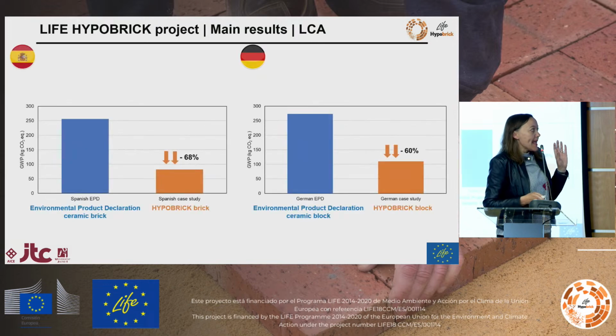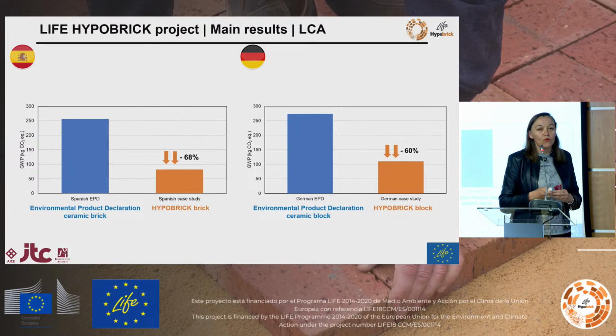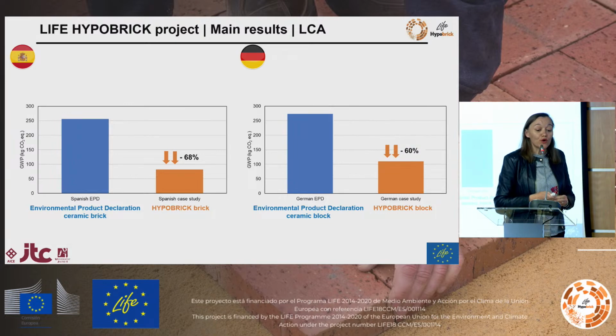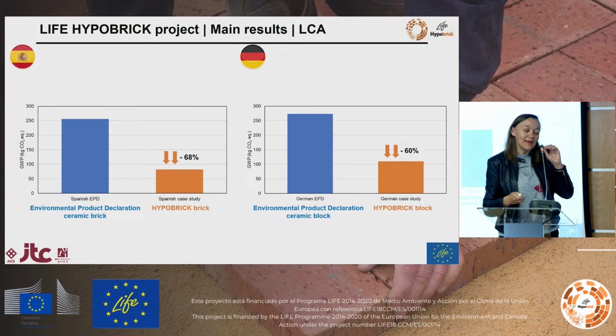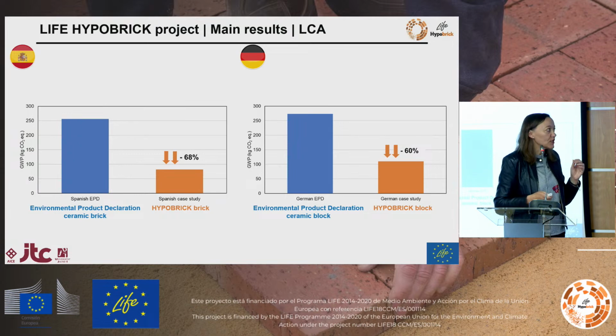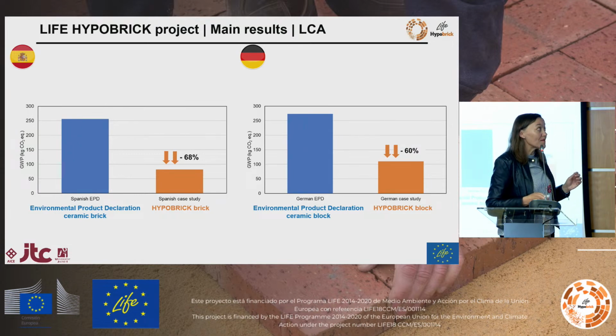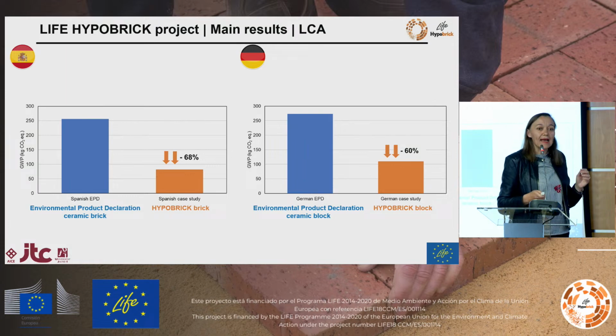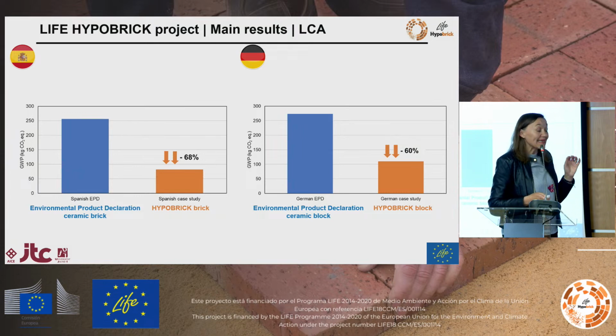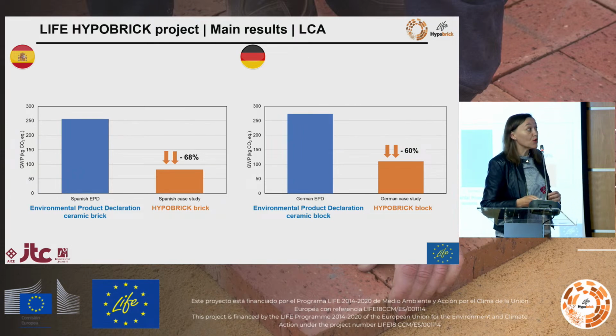From all of the results we have obtained, it is important to highlight the reduction of the CO2 emissions we have achieved. We were always speaking about 80, even 90%, because we think that when we remove the firing process, we are going to remove all of the emissions. But we also have to take into account the CO2 of the production of the alkaline activators. Taking that into account, we have been able to reduce CO2 by 68% in the Spanish case and 60% in the German case.